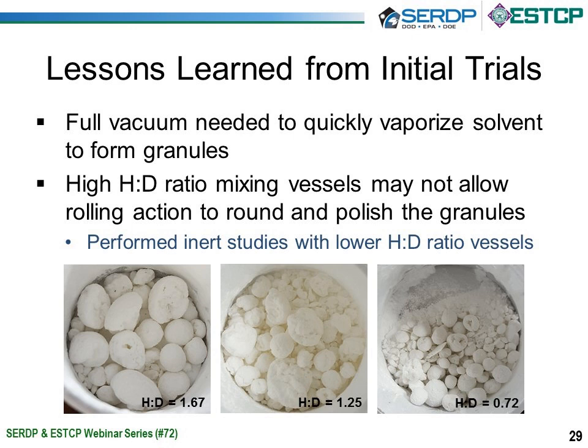And as you can see from the pictures, as you go from the left to the right, we're actually getting better and better granular formation, smaller and smaller particle size granules, as we start to reduce the H-to-D ratio. So what we found out is that we needed to go from more of a high, narrow cup to more of a hockey puck, wide, very short mixing cup.